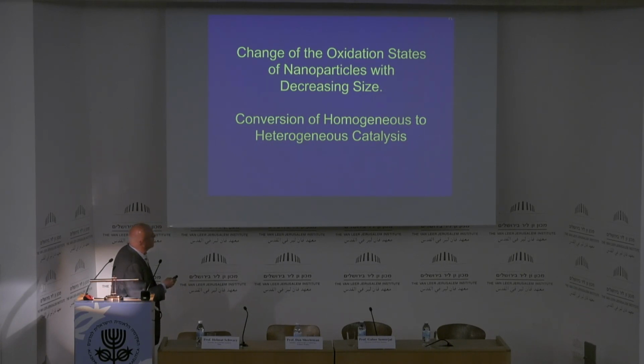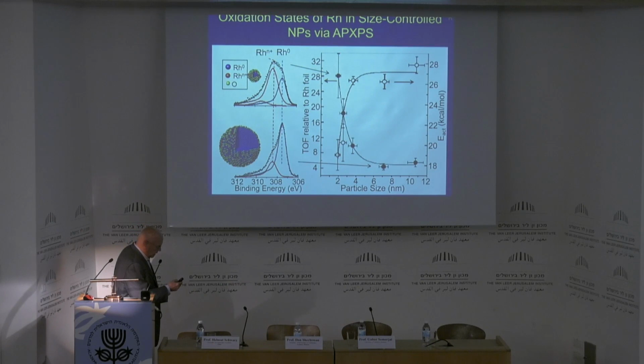What we found is that if you use a catalyst, in this case it's rhodium, and you change the size, you go to about 2 nanometer in size, the reaction is CO oxidation. There is an enormous 30-fold increase in the CO2 formation. If you look at the catalyst, you find that it's not rhodium metal anymore, but rhodium 3+. It's an oxidized rhodium, and below 2 nanometers, this oxidized rhodium is much higher turnover rate than the metal. In fact, this is what happens with all the transition metals.